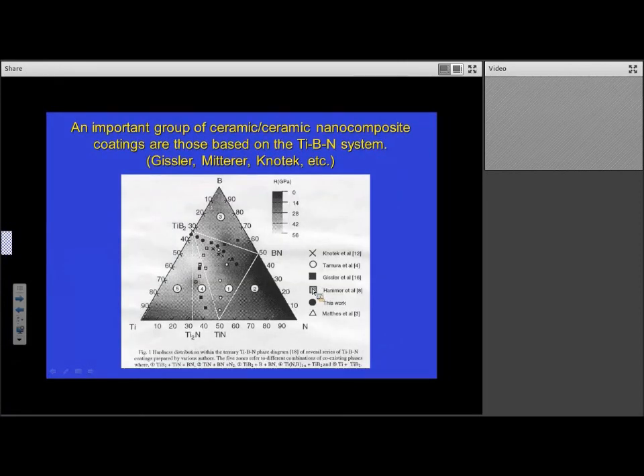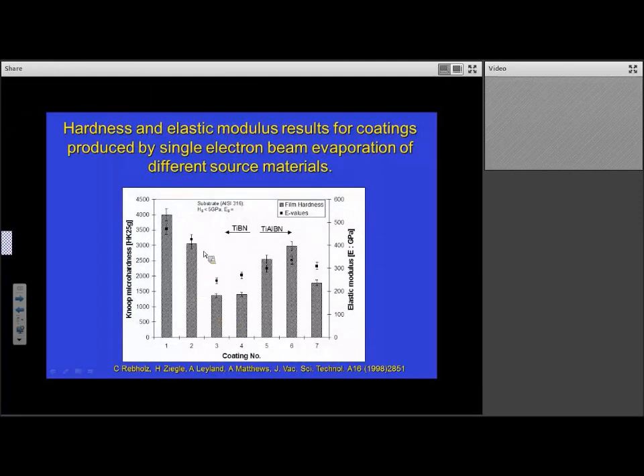Some people thought that the titanium boron nitrogen system should give good performance because it has a grain size hardening effect in this region here, and can reach hardnesses of over 50 gigapascals in this region. And a lot of work was done on this, trying to look at different places on this, trying to get to different levels of elastic modulus. But one of the issues with it was if you went to somewhere on that diagram to reduce the modulus, the hardness reduced too much. And what was found is it was useful to add aluminium to the system in order to reduce the modulus but still retain a high hardness.